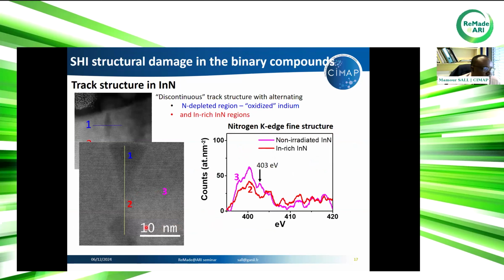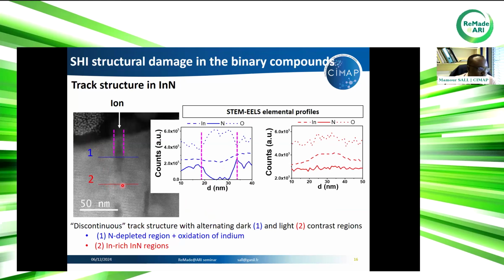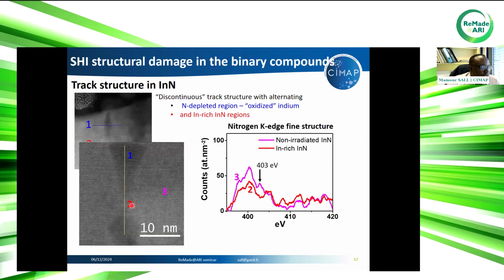So first we compare the nitrogen K-edge fine structure in region 2. Region 2 is the one we have here. In region 2, we have the indium-rich indium nitride region. So we compare the fine structure in region 2 with the fine structure in a place where there is no irradiation, so fine structure in real indium nitride.